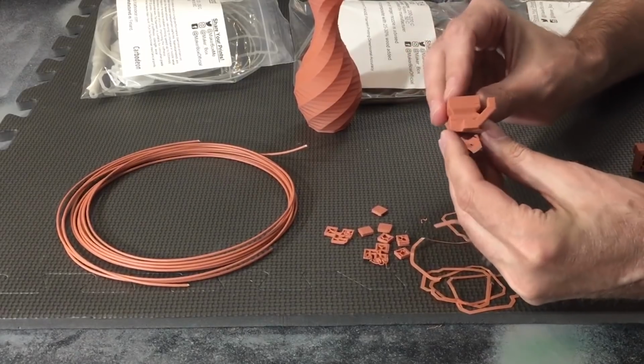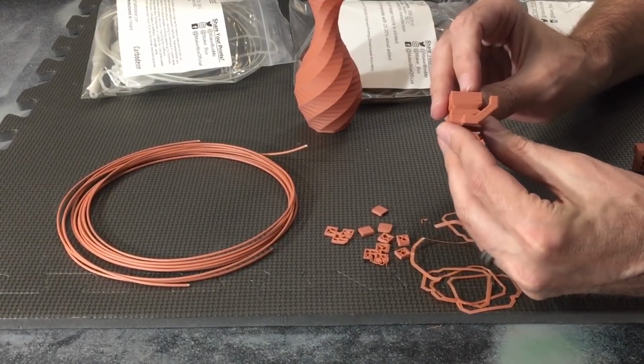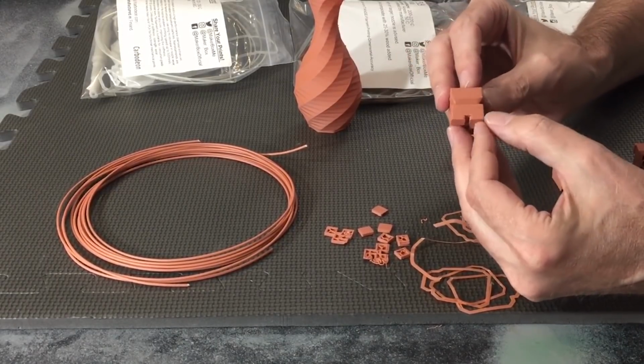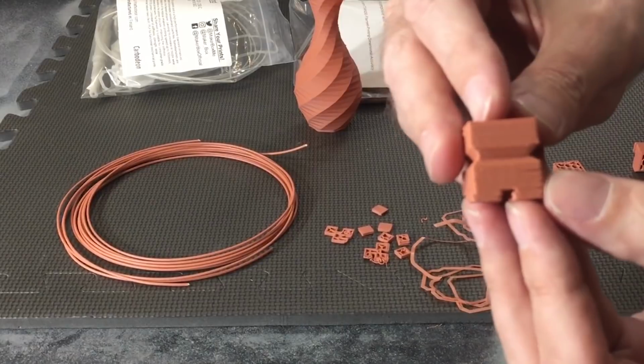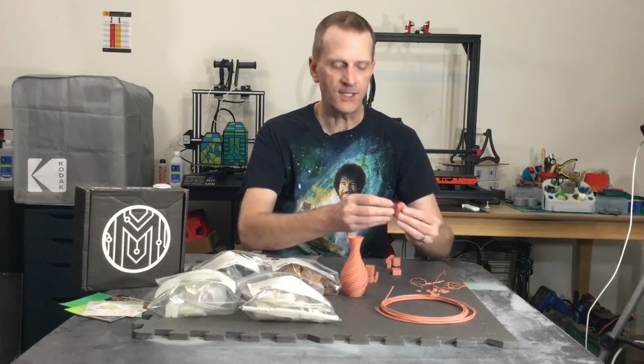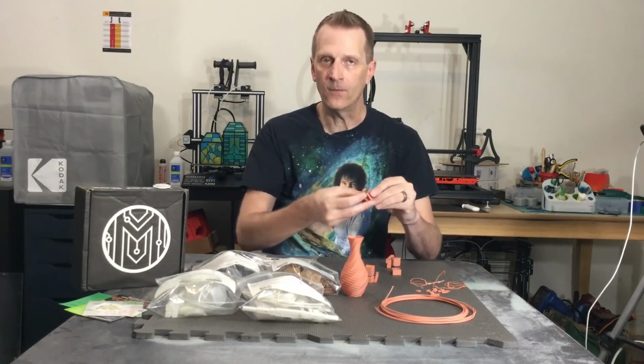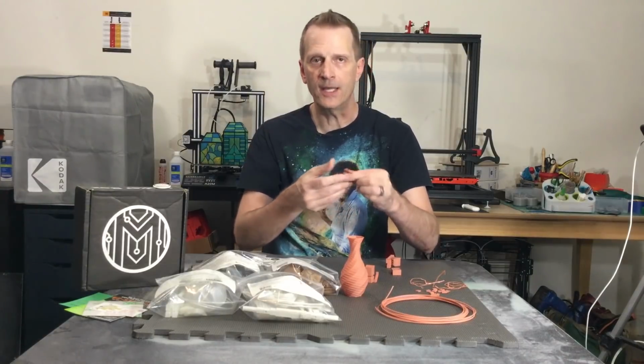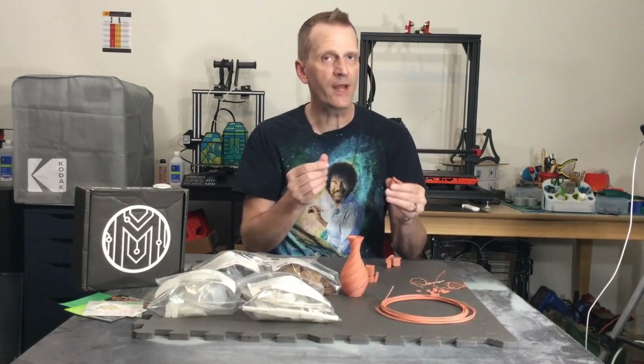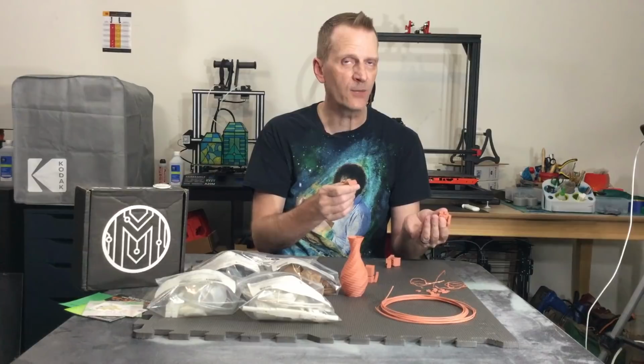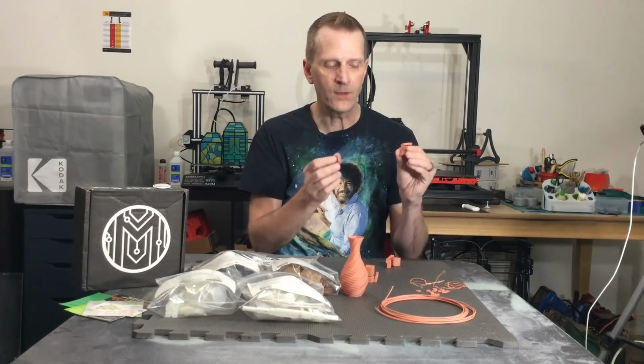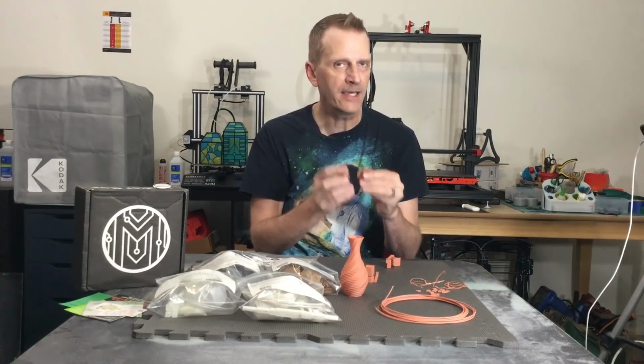It's interlayer warping. And I've never seen that before on any 3D prints, where there's interlayer warping. I hope you guys can see that. I'd never seen it. And it was brittle when it came off the print bed. It literally broke in my hand. So I knew that 220 and 85, my starting temperatures, were going to be too low. There was a strong indication that this needed high heat.